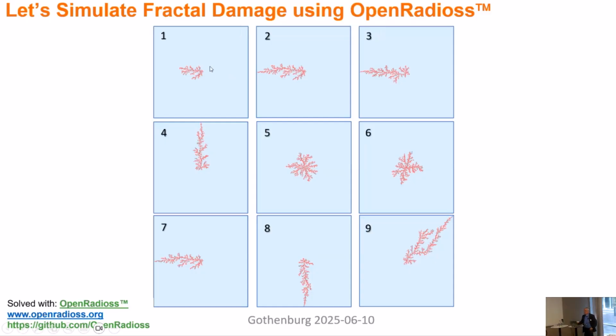You define your starting point, you define your first ending point, agglomeration point, or you don't do it, so you let it be fully random. The starting point can be totally random, the ending point can be totally random, or you define some because you have observed it somewhere on the structure. So it's fully flexible. Then you define the probability value, and then you let it run. In the starter it takes just 1 second, and you will obtain this kind of pattern based on a pre-damaged structure, where you then apply your material model and your fracture criteria, and you continue with your real load case. It can be a drop test, it can be a ballistic impact, it can be anything else. But you already have a structure which represents the reality.